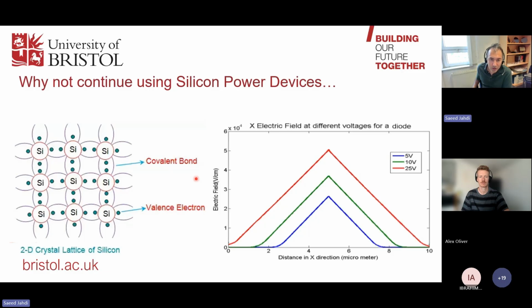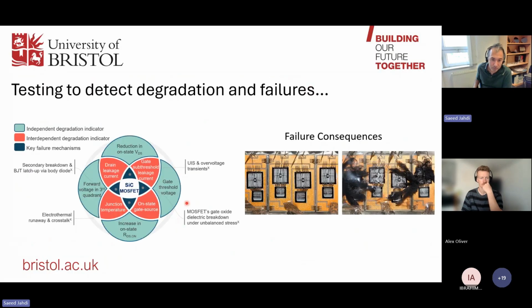So why not just continue using silicon power devices? Simply because the electric field level is limited. As you increase the voltage, this triangle here will become larger and larger. The device will become very thick. The peak electric field will eventually reach the critical electric field. If you want to expand the voltage further, the device will become even thicker and the doping will go down. And effectively, you cannot fabricate very high voltage devices with silicon that are efficient enough for very high power grid level applications. So there is a limit. We need to address that.